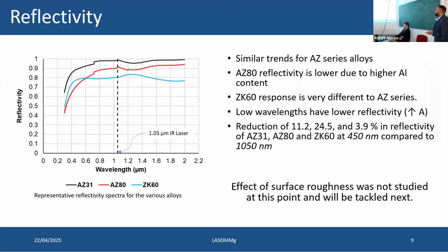So for the reflectivity results, what I received was that the AZ series, both of these, the black one and the red one, show a similar trend, but there is a difference in their reflectivity, mainly due to the difference in the concentration of aluminum in them. And the ZK series had a very different behavior than the AZ series, and this is something special, something peculiar, because most of it is magnesium anyway. So why this behavior here? To understand this, the DFT calculations will be done. And here are some of the highlights of the result.